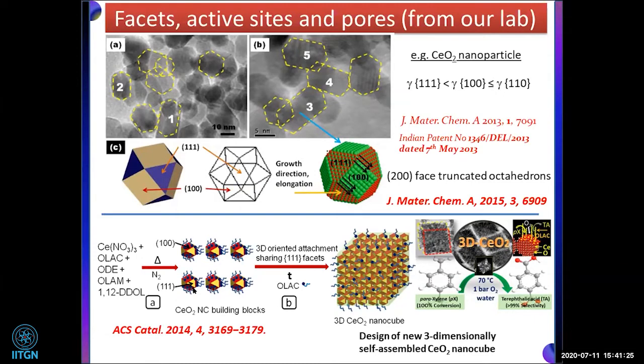Now when we keep on doing the reaction at higher temperature for a longer run, these 111 facets, which were free, went for the oriented attachment and we got a highly porous nanocube of cerium oxide, which is mainly exposed to the 110 and 100 facets only. And because of that, we got 100% selectivity or conversion of paraxylene to terephthalic acid. And you know, terephthalic acid is one of the high commodity materials, which is a billion dollar industry.